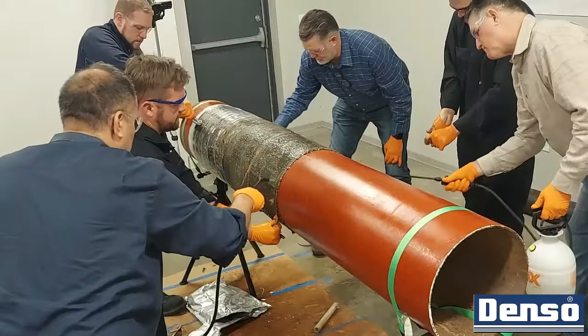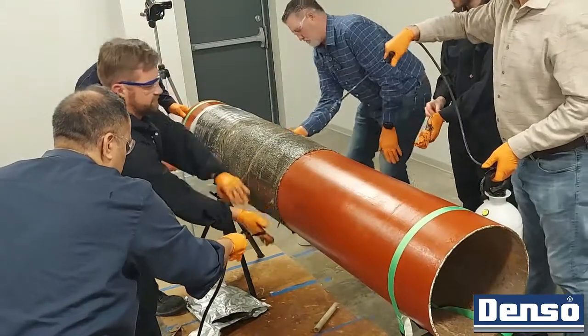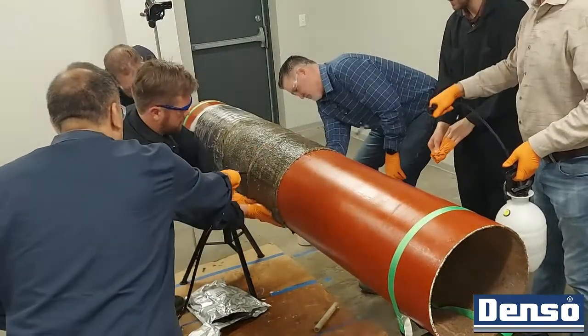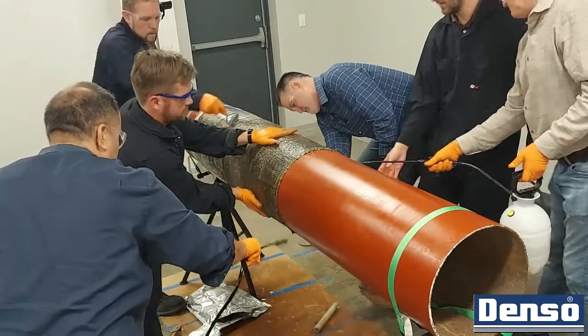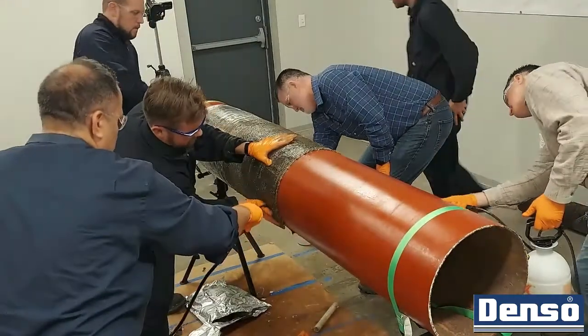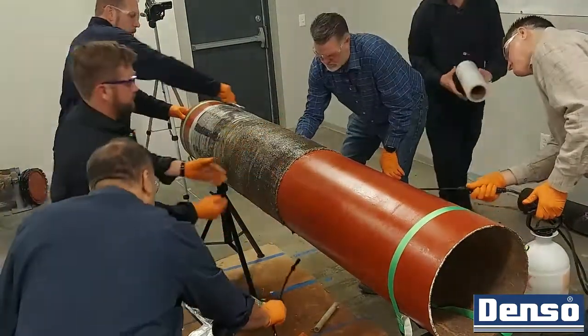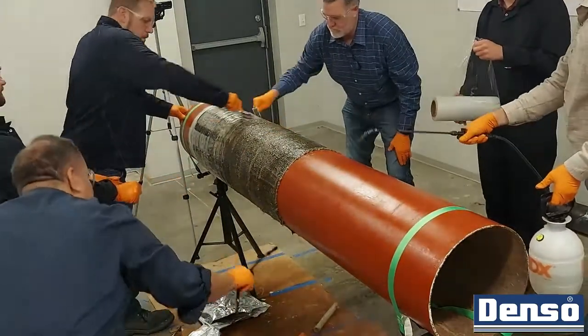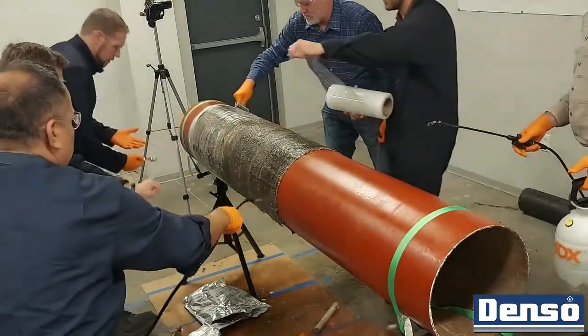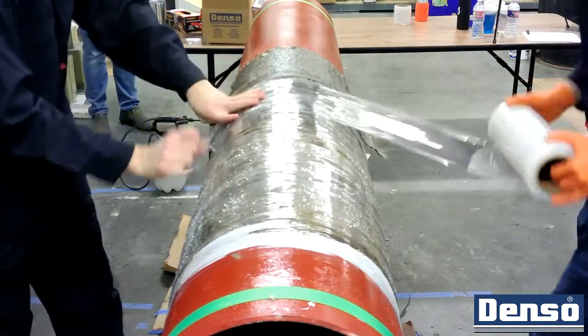This wrapping process can continue repeatedly until a stopping point is reached. Once a stopping point is reached, the final roll of bore wrap should be applied and finished with one wrap circumferentially so that it ends with fiber on top of fiber. Never leave a single layer of bore wrap hanging from the back.